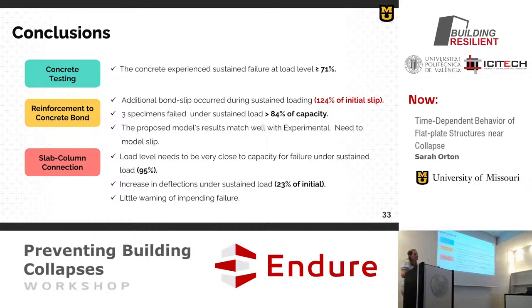Increase in deflections, definitely a lot of increase in deflections. So this is the idea of monitoring the structure. They always monitor deflections. There is an increase in deflections. It's not as much as the bond, 23% initial, but you can definitely see increases. But the impending failure, when it's just increasing and it's about ready to go, there's very little warning. You have a very short time window, which would be a problem if somebody's just sitting there monitoring it. It's like, when do we actually have to leave? Once you're worried about it, you should go.